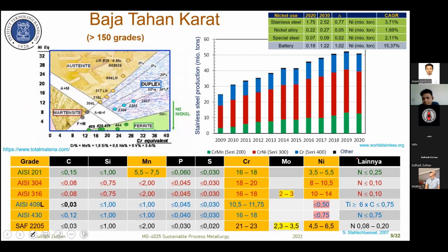If you look at stainless steel, the first or common use of nickel is for stainless steel. You see there are around 3 or 4 grades of stainless steel, which is shown here. The first one is the 200 series. The 200 series actually belongs to austenitic stainless steel. For example, for grade 201, the nickel content is between 3.5 and 5.5, the chromium is 16 to 18%, and nitrogen is less than 0.25.